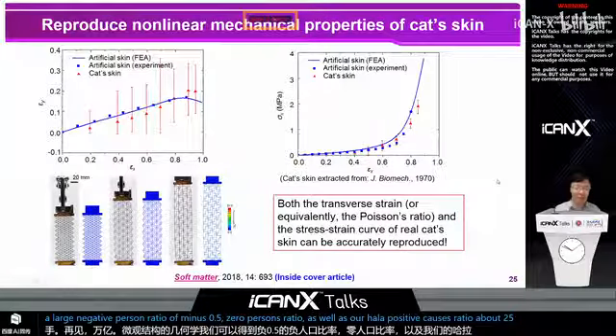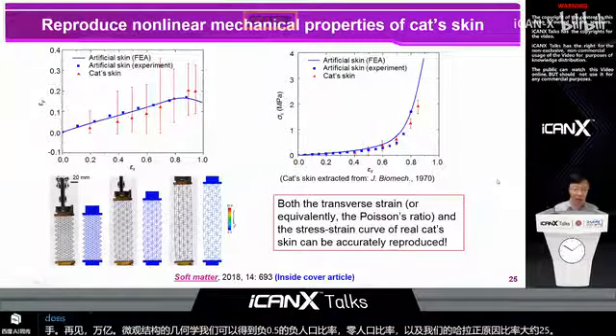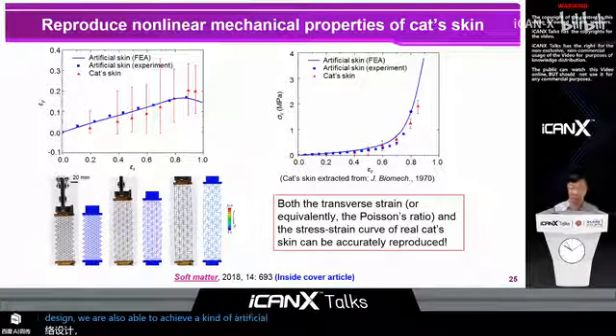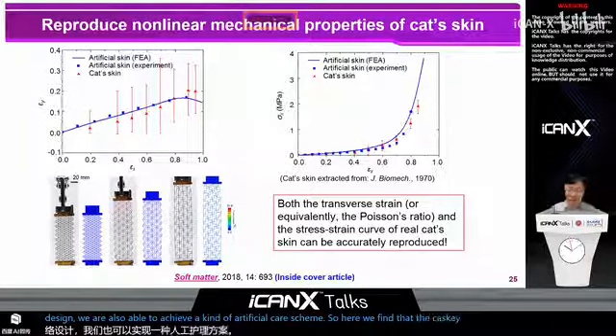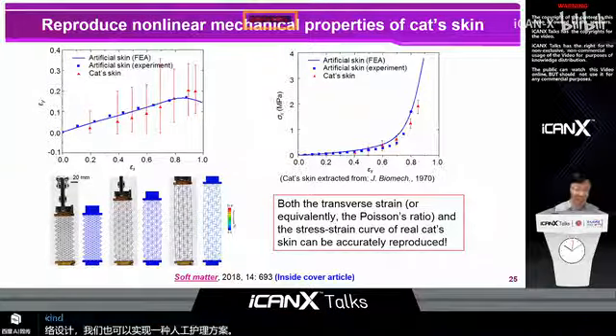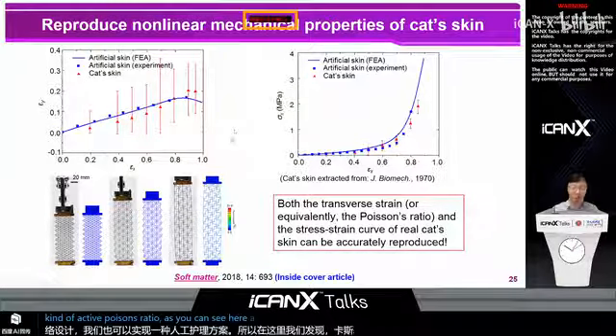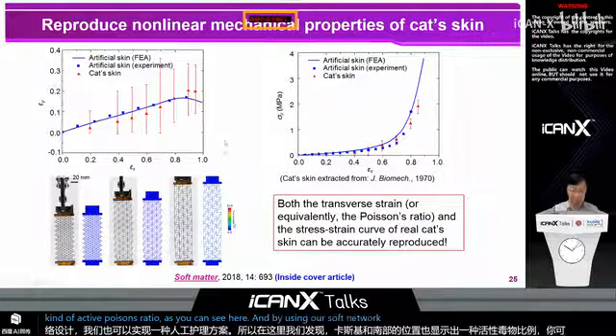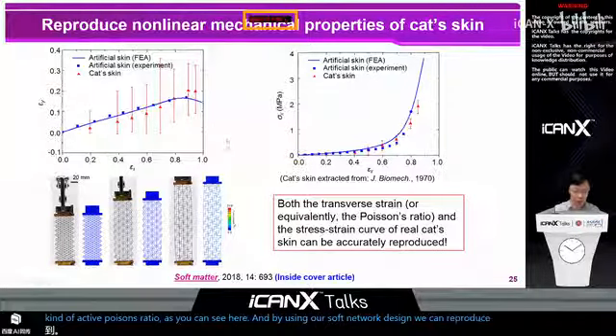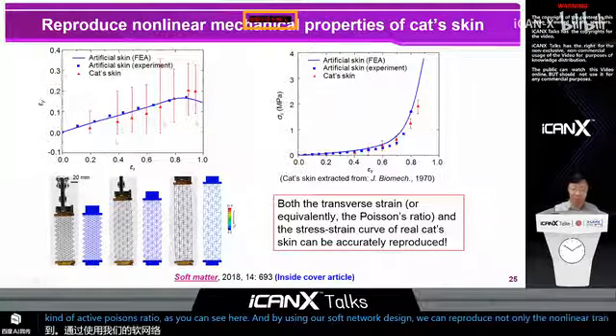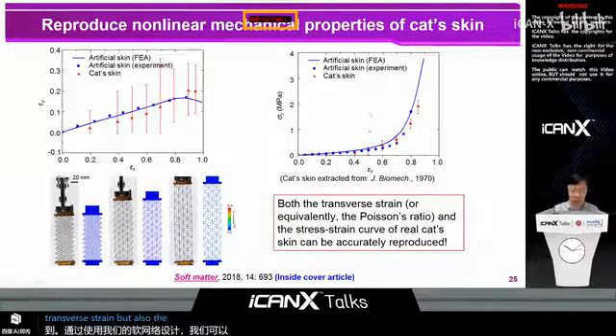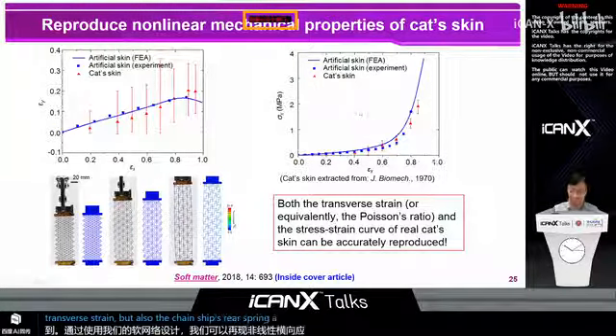And with this network design, we are also able to achieve a kind of artificial cat skin. So here we find that the cat skin at a certain location also shows a kind of negative Poisson's ratio, as you can see here. And by using our soft network design, we can reproduce not only the nonlinear transverse strain, but also the J-shaped stress strain curve of real cat skin.